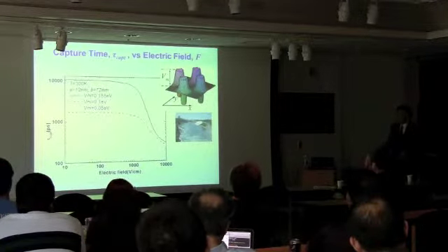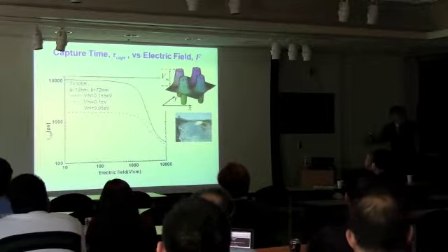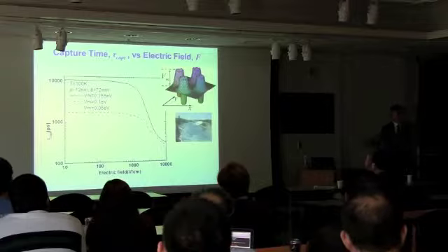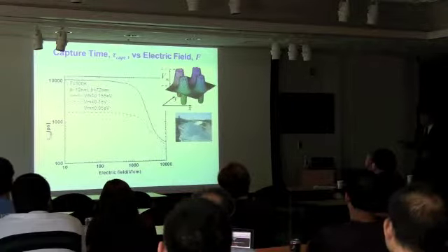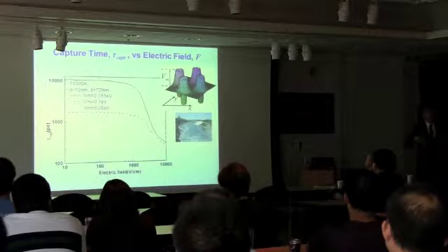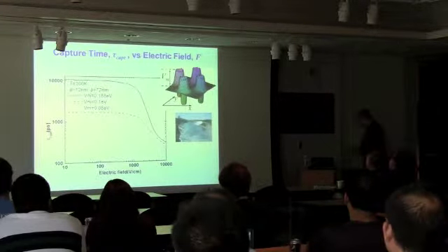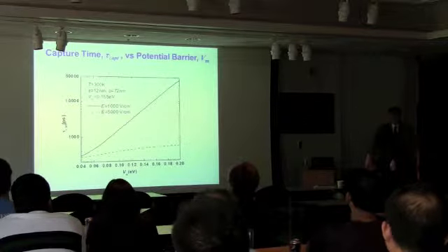So what is the idea? You need first to increase the barrier height, charging dots using outside doping, and second, don't go to very high voltages, because higher voltages in the detector will really reduce the lifetime.